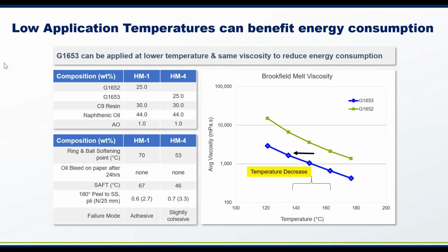So the smaller molecule design and lower viscosity is leveraged to lower application temperatures for hot melt adhesives. So this can reduce the oxidation and degradation that does occur at higher temperatures. In a personal care application, the raw material is more sensitive to application temperatures for hot melts. So the viscosity of G1653 is leveraged to reduce the application temperature some 30 degrees in this section here. Again, comparing G1652 in a hot melt with G1653 in a hot melt.